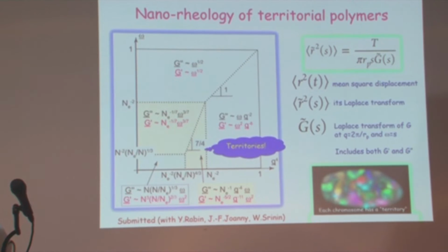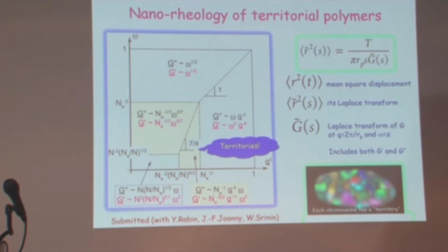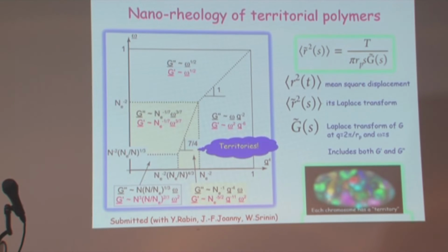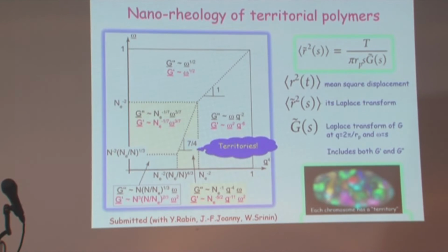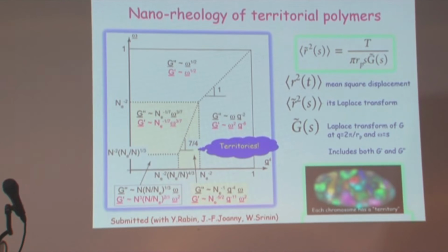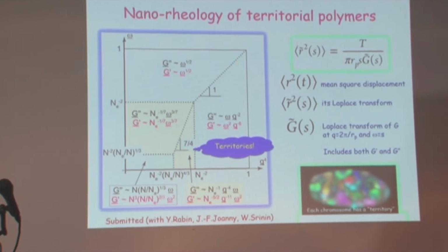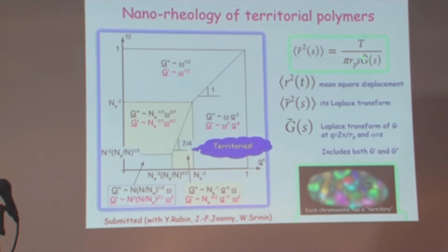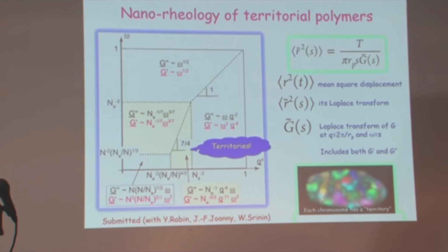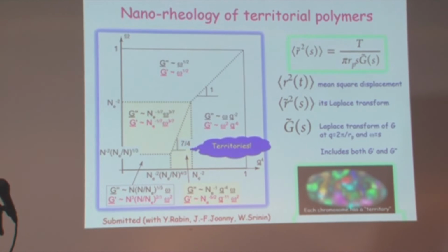So this essentially is your mean square displacement. Forget about the technical mathematical details. It's not a Fourier transform but a Laplace transform, because it's more stable. Doesn't matter. But importantly, there is particle size. And accordingly, the quantity that is here, generalized viscosity or generalized modulus, depends on the spatial scale.